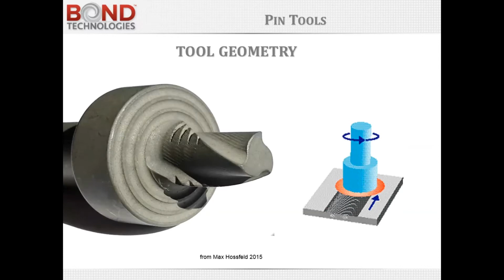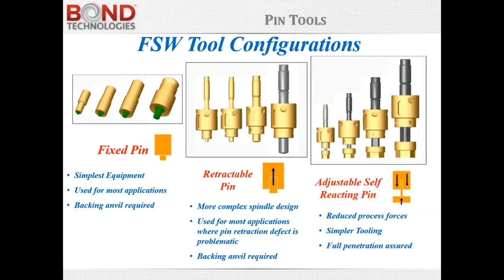Typically, these are tool steels, starting with something like H13 and going up to some high nickel cobalt alloys like MP159 or Nimonic series of materials. But the pin tool takes a lot of abuse, and so it has to be made of a very good material in order to last a long, long time.